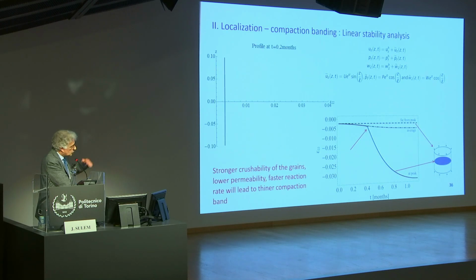And we have applied this to the problem of injection of reactive fluid and looking at the possibility of compaction banding. And you see here how the strain localizes in small, narrow zones here. And the thickness of this zone depends on the crushability of the grain. So stronger crushability of the grain, lower permeability, faster reaction rate will lead to thinner compaction bands. So here again, you see the ingredient is to take into account the heterogeneity of the dissolution process, define the appropriate length scale for it, and this length scale will control the actual thickness of the localized zone when considering this injection of reactive fluid.